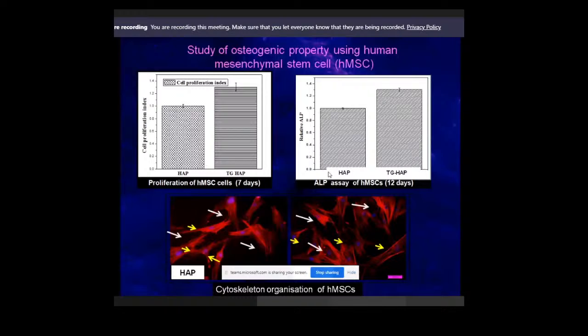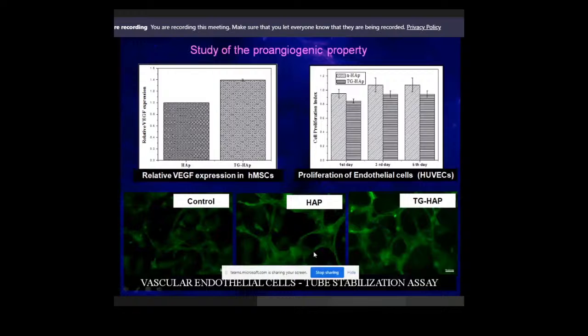When we checked with human mesenchymal stem cells, we observed an increase, may not be very high, but there is an increase in alkaline phosphatase synthesis in the case of TG-HAP. And then we checked the proangiogenic properties. The relative VEGF expression is also high, almost 1.4 times, and there is a formation of this network, which is very prominent in the case of TG-HAP.